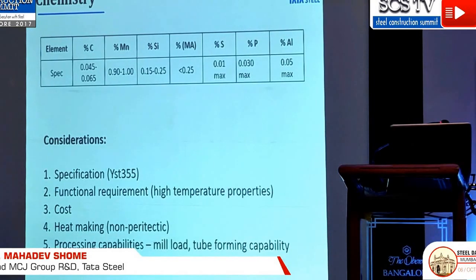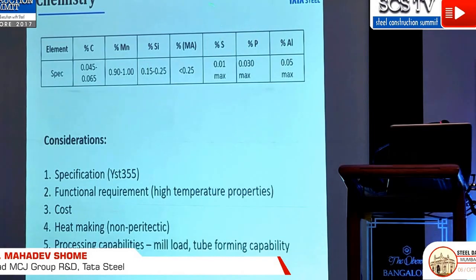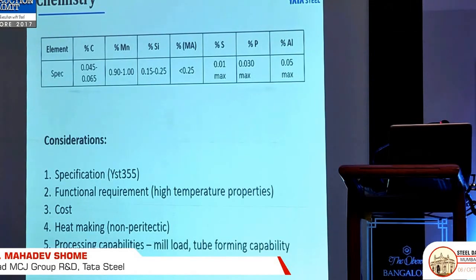Now, while going for a design of this steel, this is very standard composition with any of these YST 355 Tata Structura steels. But the trick lies up here, where you need to use a judicious amount of microalloying element, okay, to see whether you would get the fire resistance properties. Now, the internationally available fire resistant steels, even there is an IS specification with the fire resistance properties, have extremely high microalloying elements, which makes it costly, and these are really costly materials. And so, to make it competitive, the challenge was how low we can keep this value, but still attain the sort of properties we are looking for in terms of yield strength. So, these are the considerations.